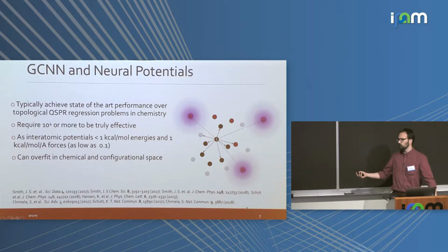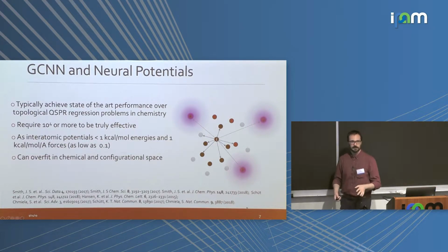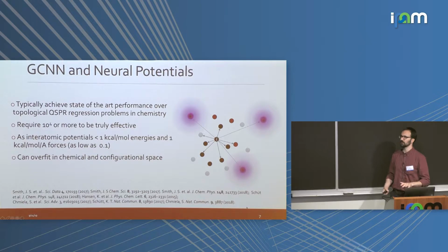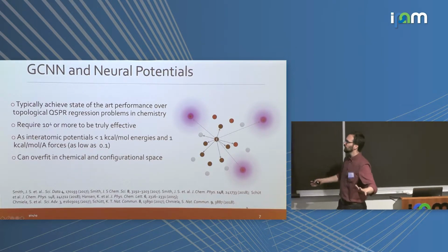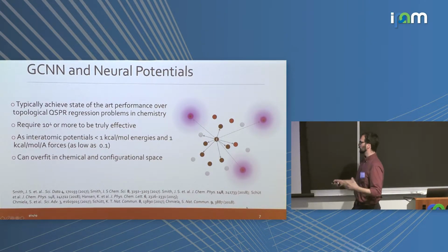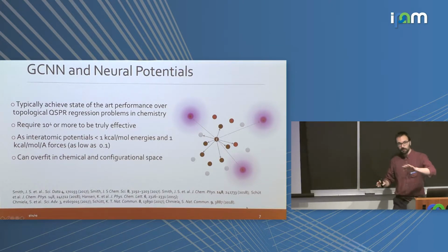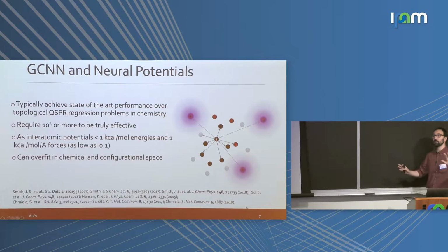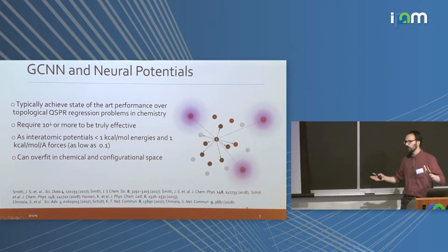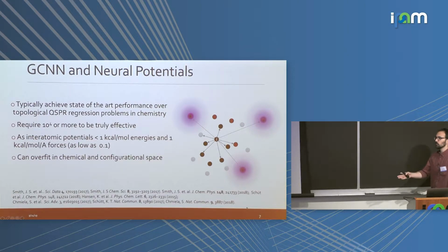In the topic of interatomic potentials, I don't know if Alexander Tkatchenko is in the audience. Yes, we got a great introduction. He gave us all the benchmarks, and I would just say that it's absolutely true. It can work. If you train on the right ensemble, and you sample on the same ensemble, 0.1 kcal per mole, same amount for the forces, so it's as good as it gets. That's way better than chemical accuracy. It's getting to almost, not quite, but close to the numerical noise of the DFT that you would be running, maybe.